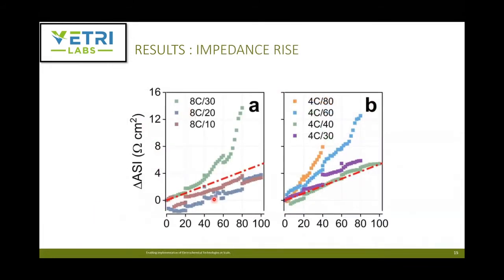So in addition to the capacity fade, they looked at the impedance rise, as we discussed earlier. So this is the 8C at 30% SOC, 20 and 10. You can see at lower state of charge, it's fairly linear, but even at 30% SOC, at 8C, it becomes a nonlinear rise in impedance. And as you go towards lower charge rate, you're getting at least a little bit more SOC, you got up to say 30% and 40, and then 60 and 80 became nonlinear.